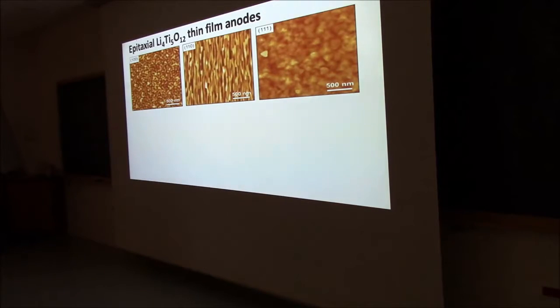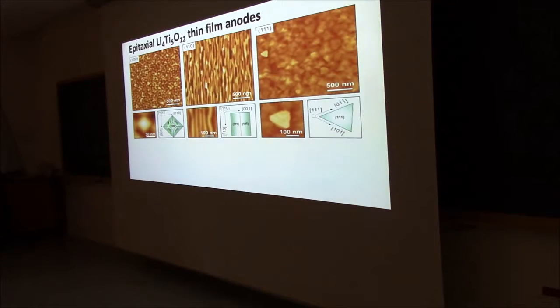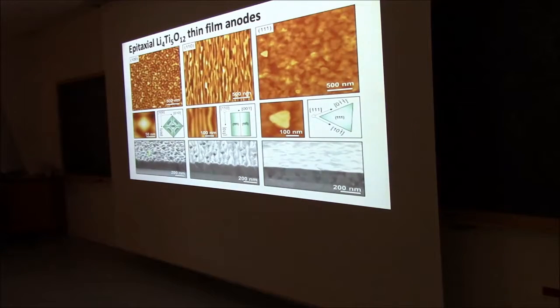And this is also what you see back in the AFM pictures. Squares, lines, and triangles. If you zoom in, you can really understand them, similar as the other spinel I've shown you before, the lithium manganese oxide. Same thing, spinel likes to be 111 crystal facets, so in the end you will see a little bit of pyramids, smaller than what I showed you before, these rooftops, and something which is very flat.